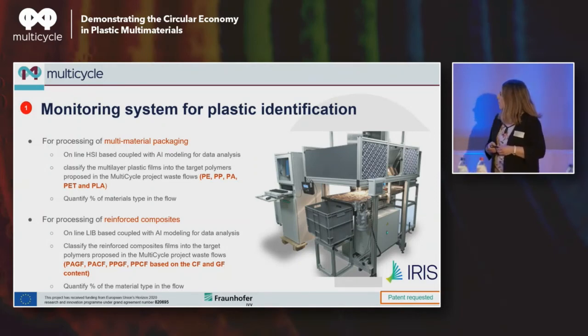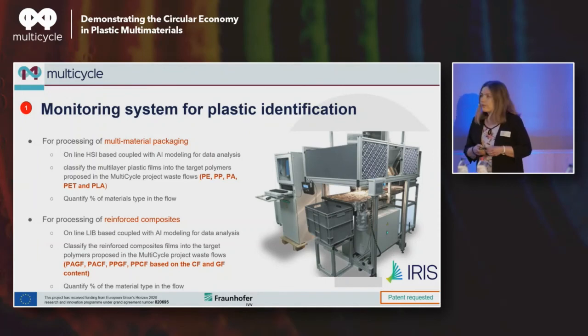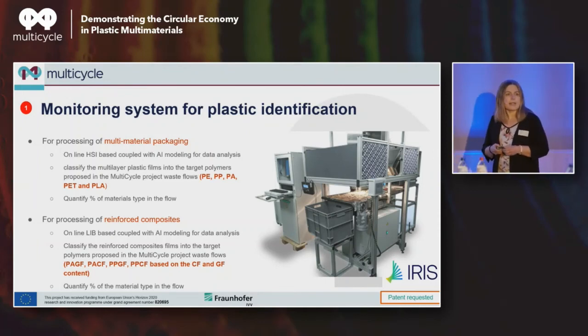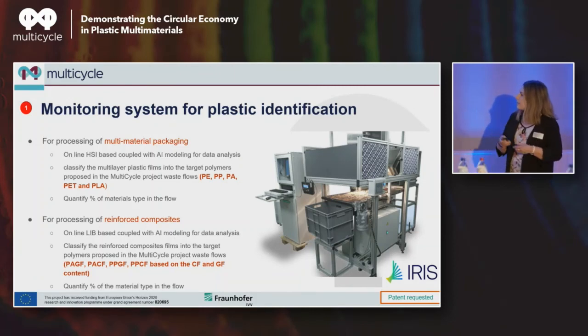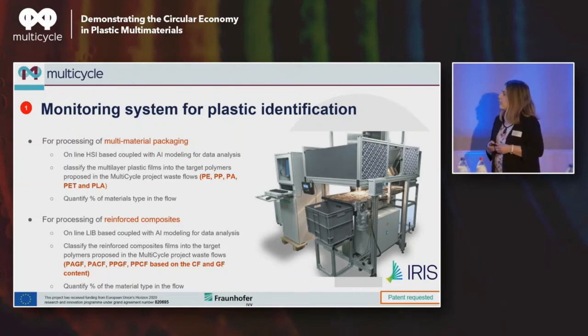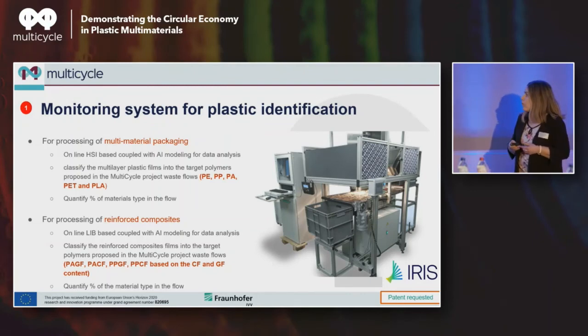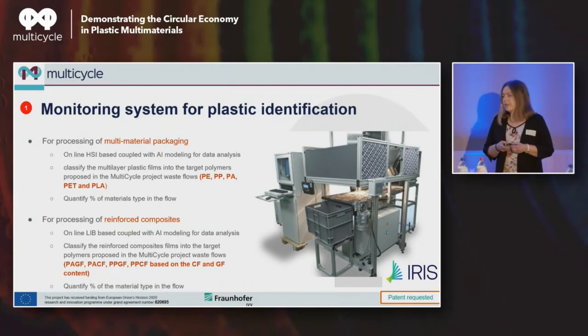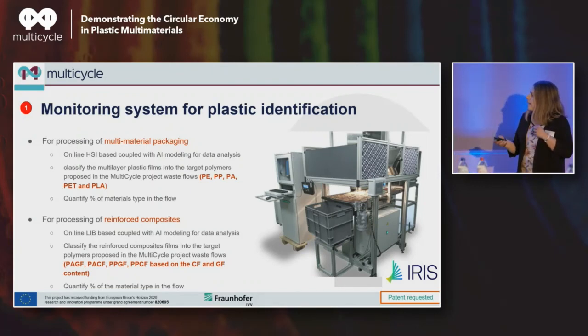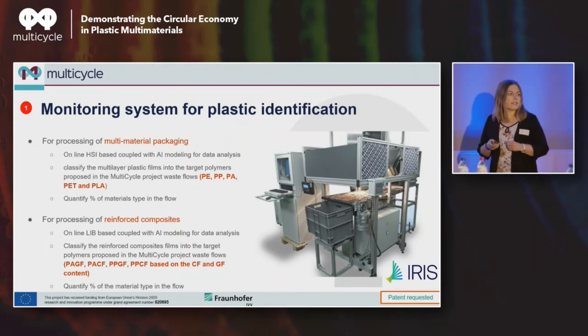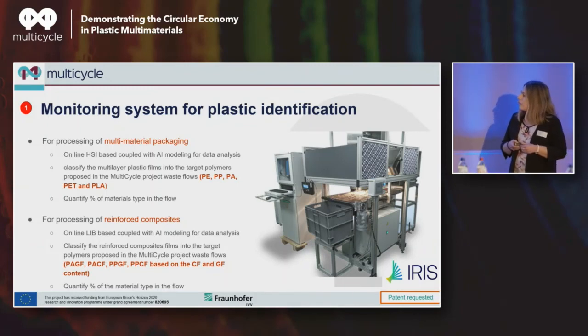And also, we were able to quantify the percentage of each type of material in the flow that comes into the process. The second one was dedicated to the reinforced composite. In this case, the technology behind is different. It is laser induced breakdown spectroscopy, which is LIBS, coupled again with an artificial intelligence model for the data analysis. And in this case, we were able to classify the reinforced composites, PA glass fiber, PA carbon fiber, PP glass fiber, PP carbon fiber, based on the carbon fiber and the glass fiber content of these flows. Again, we were able to quantify the percentage of the material type in the flow.